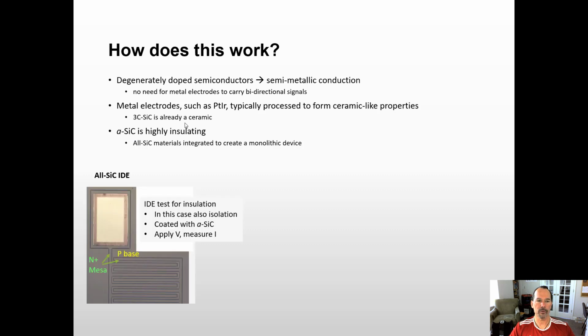So a test of our system is the following. We're relying on PN junction diodes to prevent leakage currents between those adjacent conductors. And we're also relying on amorphous silicon carbide on the top to cap the device to prevent short circuiting in a wet solution like the brain. So here we see an interdigitated electrode or IDE device with two mesas, a P base with an N plus conductor. These are comb drive type structures. So we apply a voltage, measure the leakage current, and we continue to apply the voltage till we get breakdown.